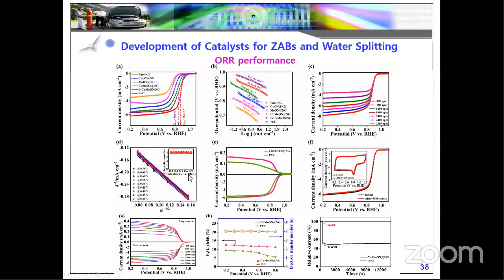We want to go to RRDE, because RRDE is one of the techniques to calculate the hydrogen peroxide liberation. If the hydrogen peroxide liberation is lower, that catalyst is good compared to materials with very high hydrogen peroxide liberation, because hydrogen peroxide may make the electrode corrosive and may reduce the durability. You can see this one is the disc current and this one is the ring current, and from the ring current and disc current we also calculate the hydrogen peroxide yield. Our catalyst is less than 15 percent, almost 12 or 10. So our catalyst has a lower hydrogen peroxide yield. Many catalysts have a higher hydrogen peroxide yield, which may destroy the stability. And the number of electrons is almost equal to the commercial platinum catalyst.